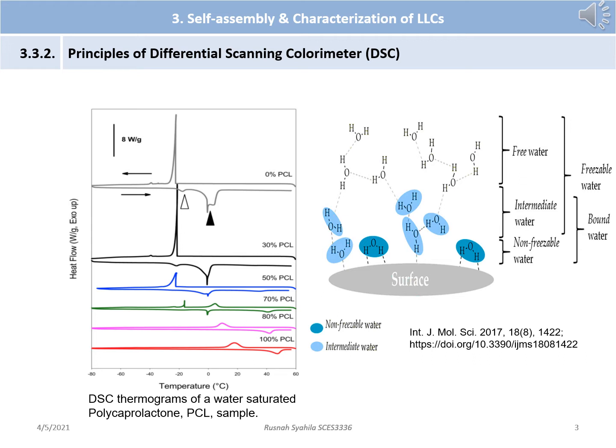When the system is sufficiently diluted, free water is present in it, which is assumed to have similar physicochemical properties to pure water. Its presence can be detected by so-called sub-zero temperature differential scanning calorimetry by the appearance of the melting peak on the DSC thermogram at about 0 degrees Celsius. The disappearance of the melting enthalpy of water, that is, the disappearance of free water, coincides with phase changes occurring in the liquid crystalline structure. The knowledge of the proportion of varying types of water is important to get information on the structure, which has a strong effect on drug release from pharmaceutical formulations.